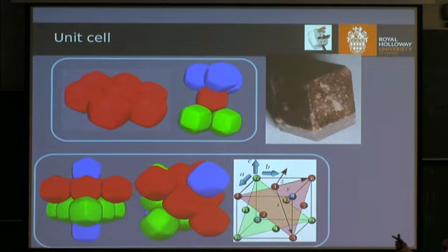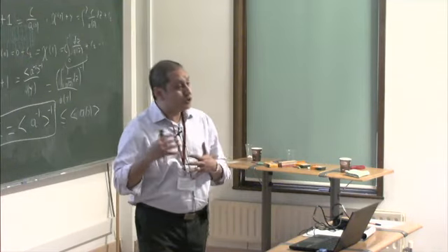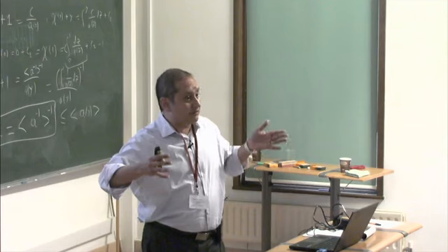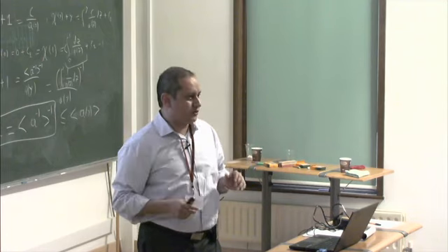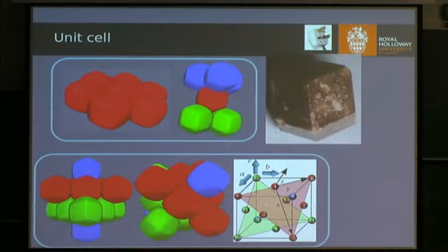One of the things we assume in these models is that even if individually crystals are anisotropic, in an undeformed aggregate the overall orientations of the crystals should be random enough that the overall fabric of crystals should be isotropic. That's the idea here. And for an isotropic FCC fabric, we decided to pick the rhombic dodecahedron as our choice of grain. So we have a unit cell of 14 grains here.